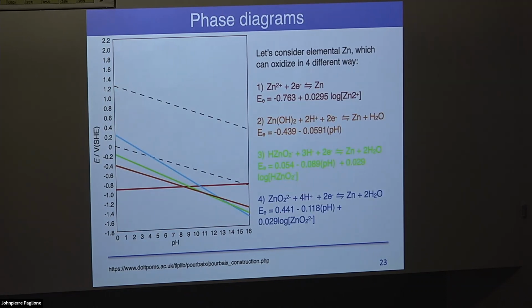So now we're going to look at actually constructing the Pourbaix diagram for an element. This is a relatively simple Pourbaix diagram, the one for zinc. It basically has 4 lines, and each one of those lines is electrochemical potential versus pH. This is because in solution, zinc has 4 stable states, depending on the pH or the electrochemical potential. We can have Zn2+, we can have zinc hydroxide, we can have HZnO2-, and we can have ZnO2 2-. Each one of those, depending on the half-cell reaction, has its own electrochemical potential. This is basically y equals mx plus b, or electrochemical potential versus pH, so they all have their own slopes.